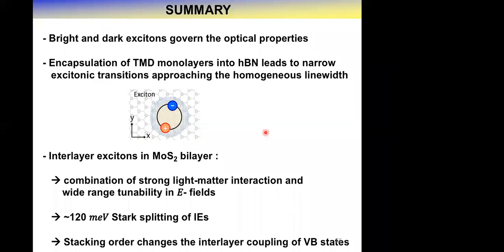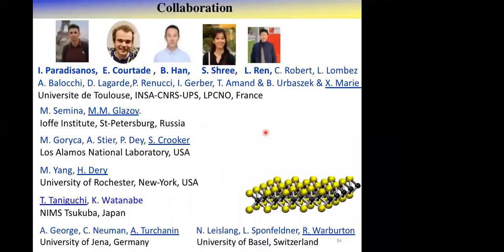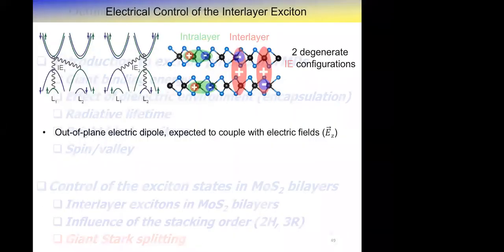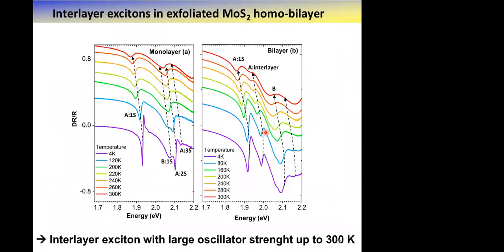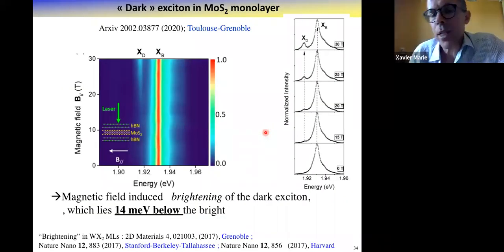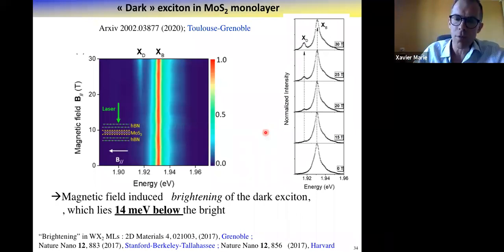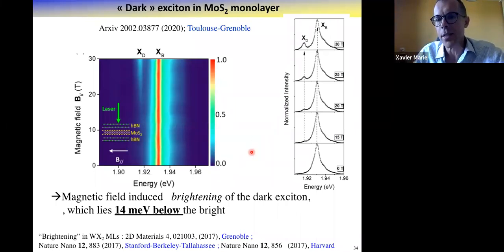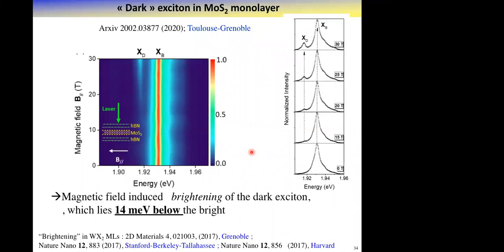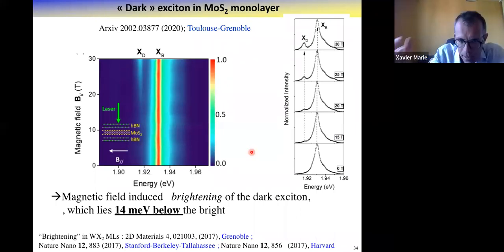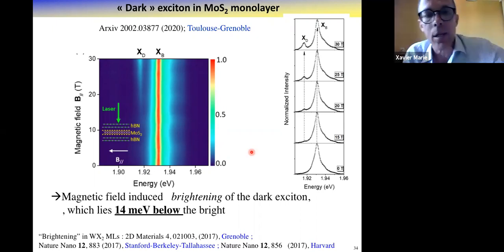Okay, so we were wondering why, in the experiment with high magnetic field, when you see the dark exciton in molybdenum diselenide or disulfide, don't you see any effect of Zeeman splitting in 20 Tesla? Yes, for sure, but here we did not resolve the polarization in this experiment. Of course, you have all the work on Zeeman splitting, but here it's clearly a non-polarized experiment where we focus on just the identification of the brightening effect, or how we can give oscillator strength to the dark exciton. Okay, so you don't see the splitting into two peaks. We did not, it's a specific configuration where we did not analyze the polarization.